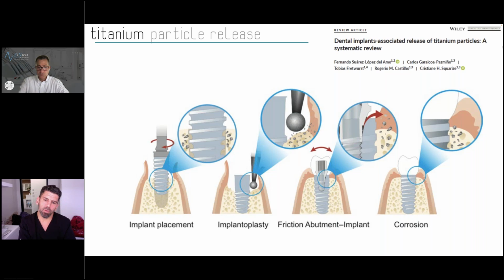The next occasion is when we do implantoplasty. This has become a very popular method to treat peri-implantitis, where you take a burr and basically remove the outer surface of the implant. And if you've done that, you know that there are a lot of titanium particles that spread out everywhere, and it's virtually impossible to clean. Other instances could be the friction that occurs at the abutment and implant interface because of the micromotion and micromovements. And as we talked about, corrosion is a phenomenon that occurs with any metal, and titanium implants are not free from corrosion either.